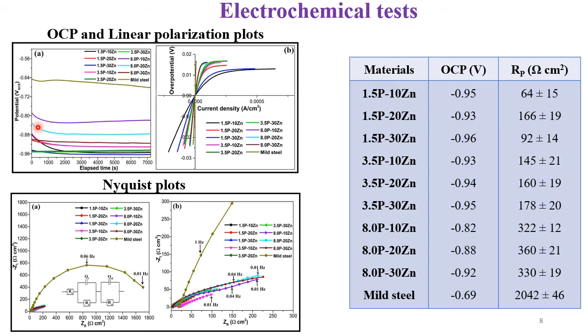Along with that, the OCP of all the hybrid samples has been found to be more active than the protective potential of steel, which is around minus 780 millivolt versus saturated calomel electrode. And the polarization resistance of all the hybrid samples has also been found to be much lower as compared to the mild steel, which could be seen from the table here. So the most important objective of our work has been satisfied here, that the OCP of all the hybrid samples has been found to be more active as compared to the protective potential of steel.